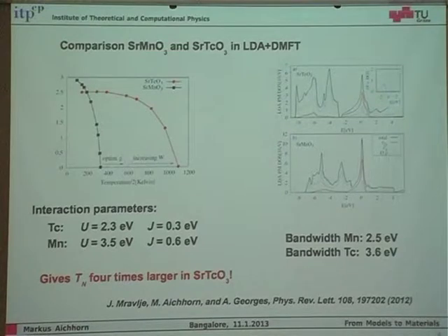That was in this symmetry broken phase, but still single-site DMFT. So there is no intersite self-energy, still a local self-energy. So when you do this for these 2 compounds, you end up with a Néel temperature of roughly 1000 Kelvin, given this factor of 2, for the technetium, and a Néel temperature of here it's 300 plus minus for the manganese. So the numbers come out, or at least the ratios come out very nicely.